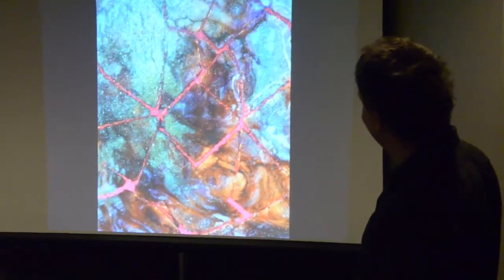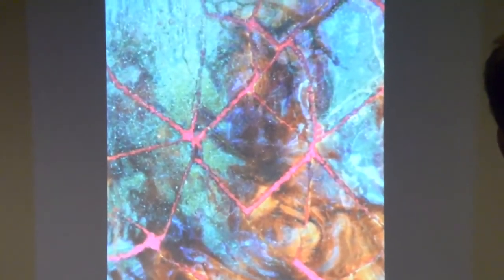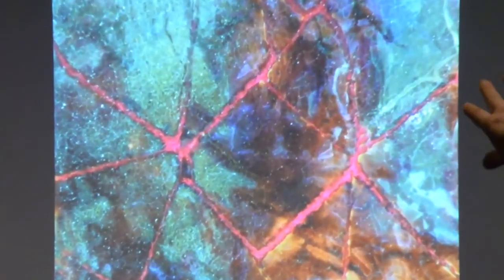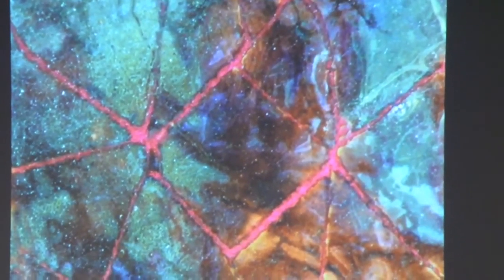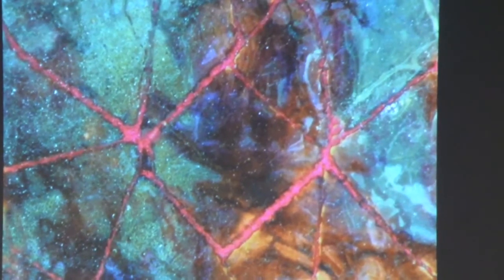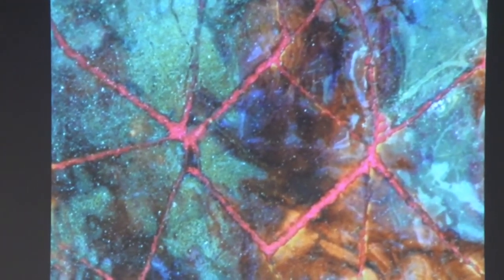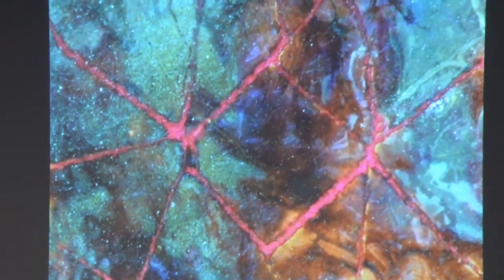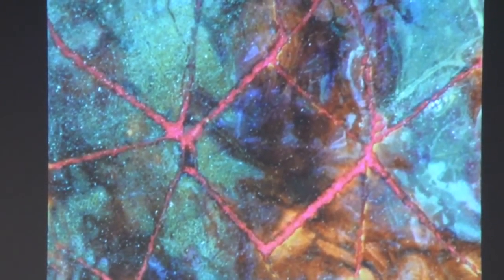This is the same Vulcan glass where I've done these swirly amber with silver amber colors, and after I've got a cool sheet, crack it, and lay the pieces out, and then fill those gaps with a nice red, and then refuse it up. And that'll get me the quarter-inch thick.